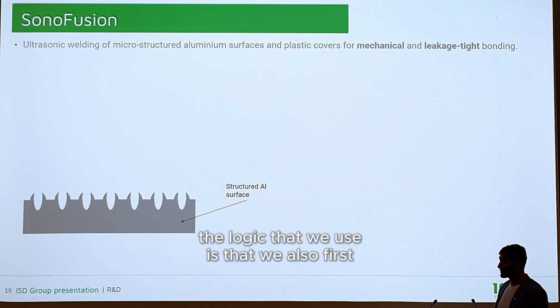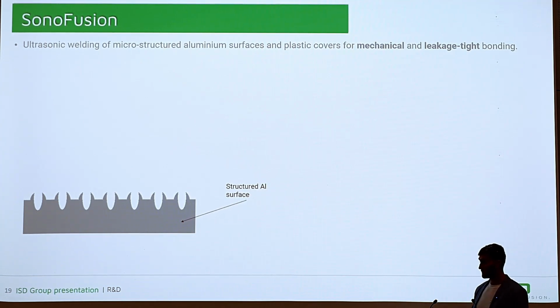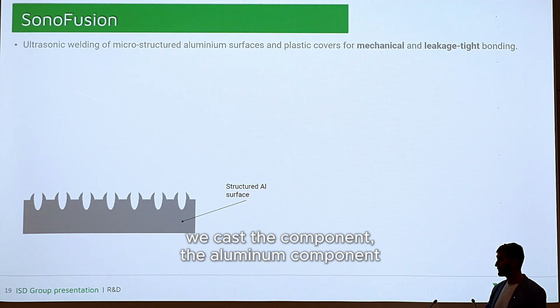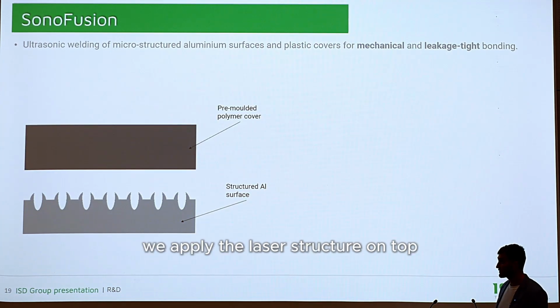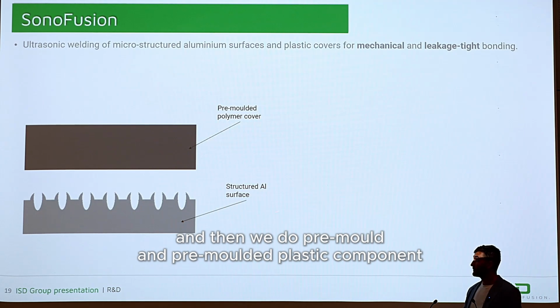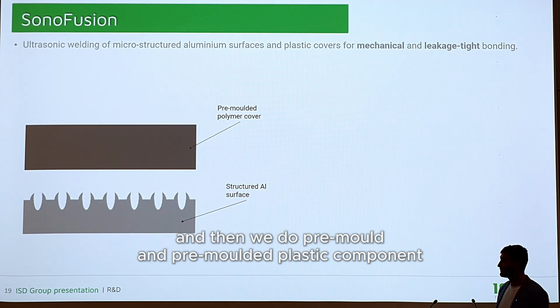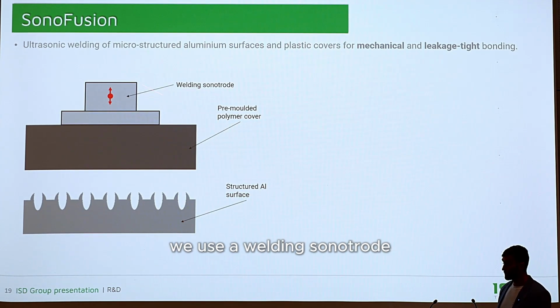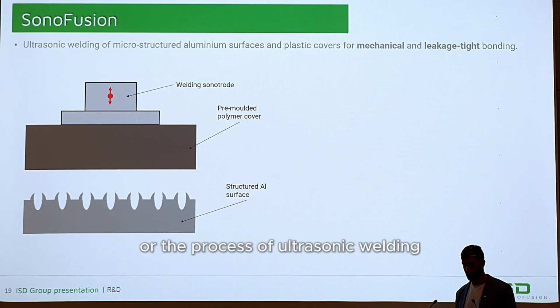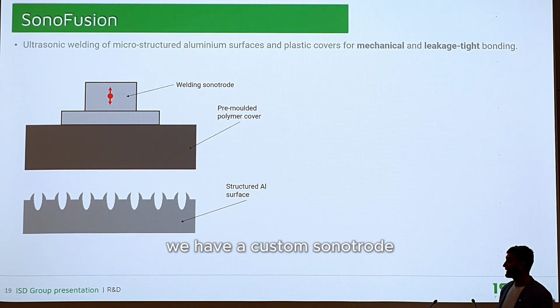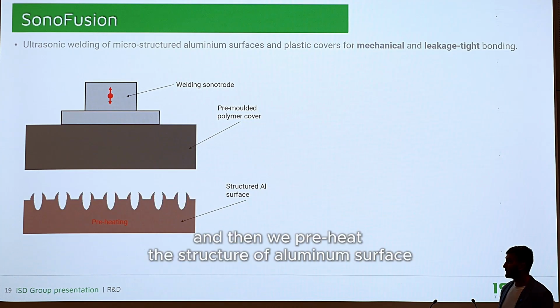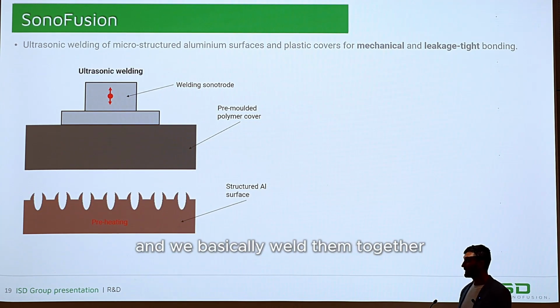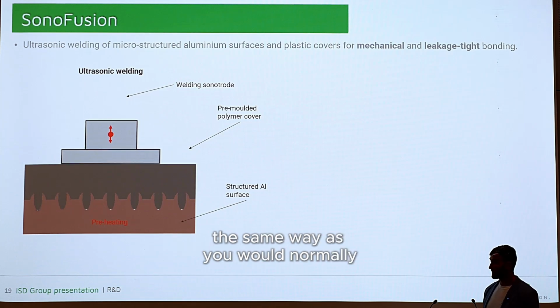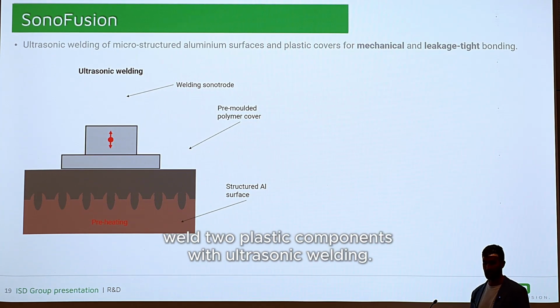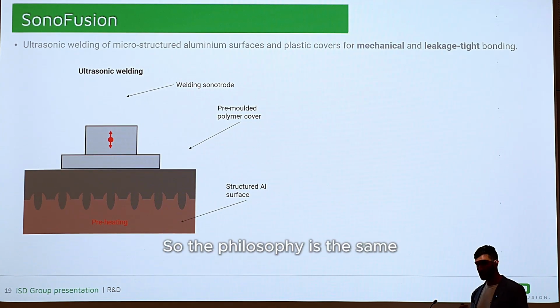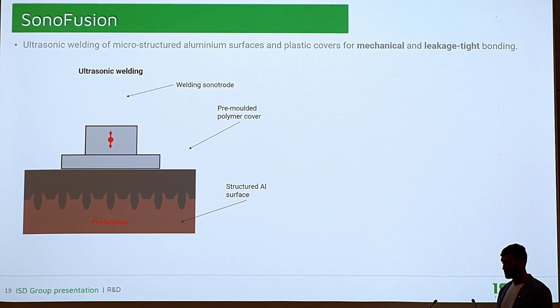So in this case, the logic that we use is that first we cast the aluminum component, we apply the laser structure on top, and then we do a pre-molded plastic component. We use a welding sonotrode. If you know ultrasonic welding, we have a custom sonotrode. Then we preheat the structured aluminum surface and we basically weld them together the same way as you would normally weld two plastic components with ultrasonic welding. So the philosophy is the same.